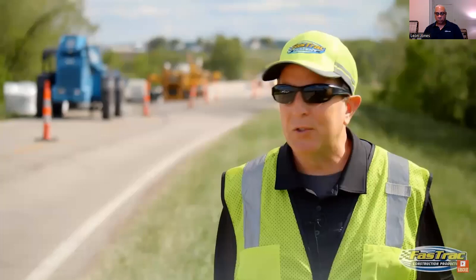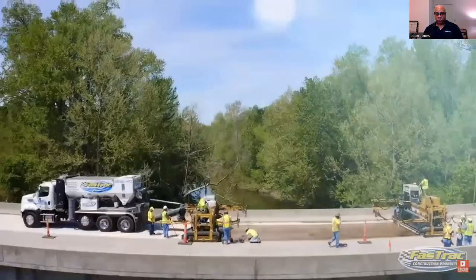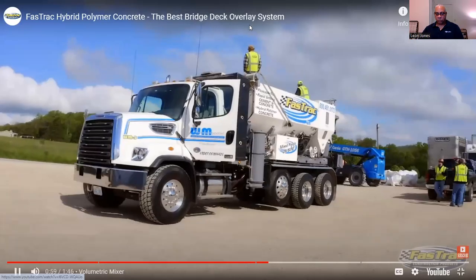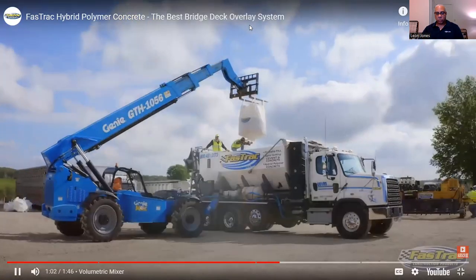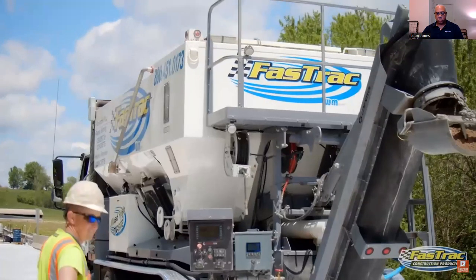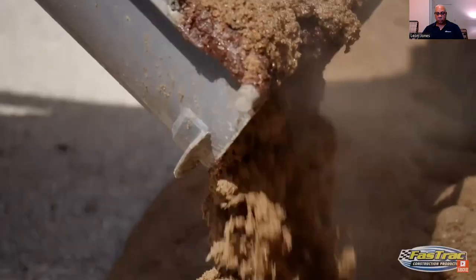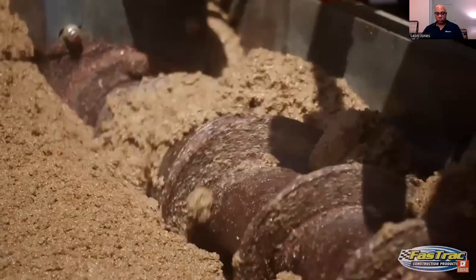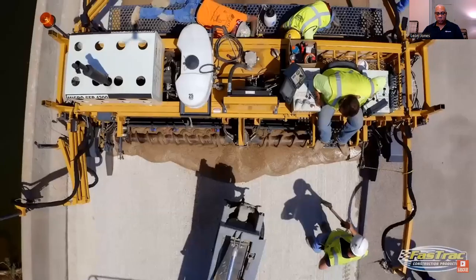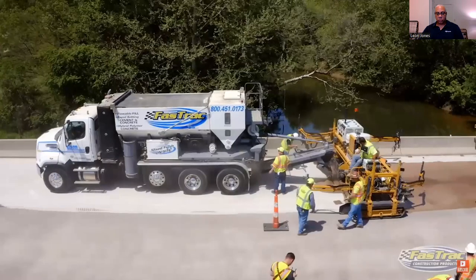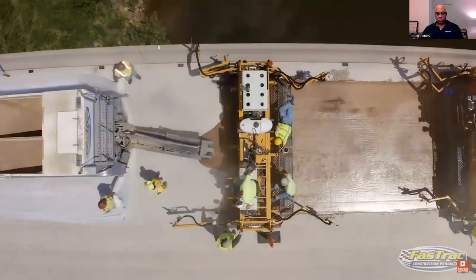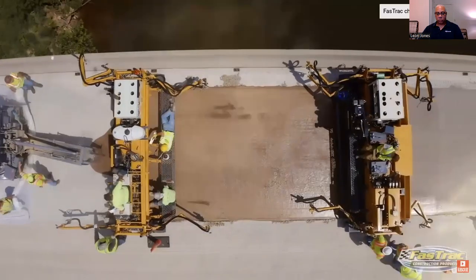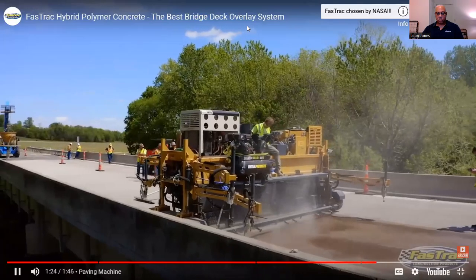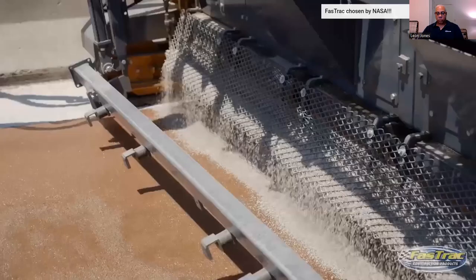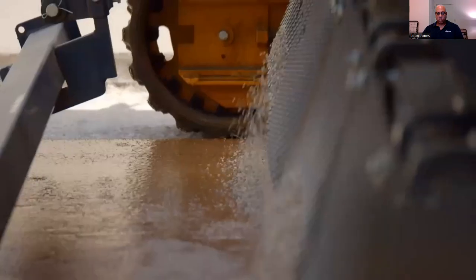We expect this bridge to have many more years of service, and the overlay itself we expect to last at least 30 years. We also utilized our specially engineered and designed volumetric mixer to produce the hybrid polymer concrete today. It's a 2-part resin system, and we get a consistent mix at all times. We also have a specially designed and built paving machine that can put hybrid polymer concrete down from a 1/2 inch overlay up to 12 inches if necessary. This material allows for the addition of a friction aggregate on top for added safety, provide not only a nice ride surface but also a safe surface.